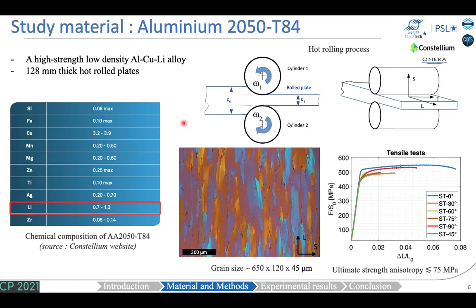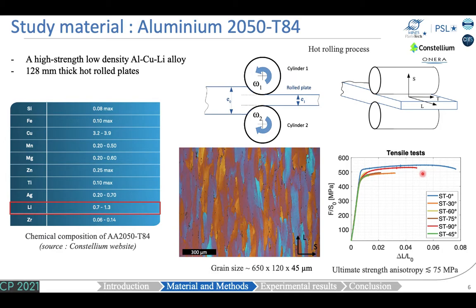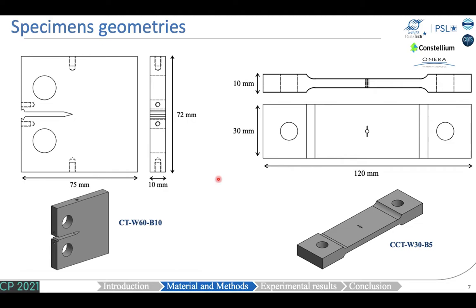The 2050 is an aluminium-copper-lithium alloy. The addition of 1% of lithium in the composition improves the material performances while reducing its density. The rolling process has a big impact on the microstructure, where grains are elongated in the L direction, the rolling direction. It also introduces mechanical anisotropy. The best mechanical performances are obtained in the principal directions of the LS plane: the rolling direction L (blue curve) and the through-thickness direction S (red curve). Considering ultimate strength, a maximum difference of 75 MPa is observed.